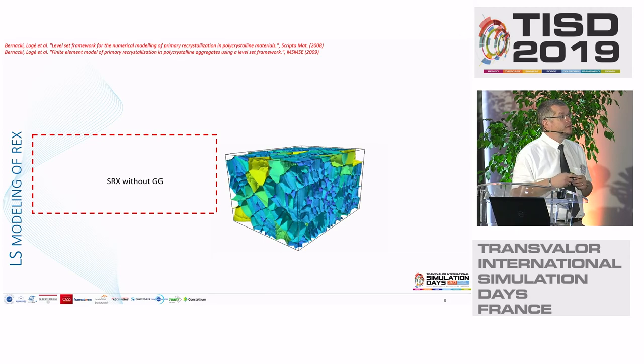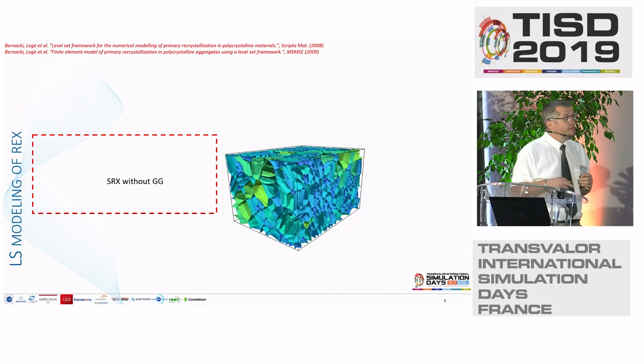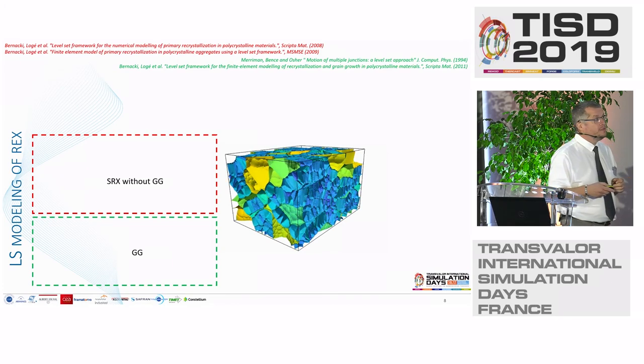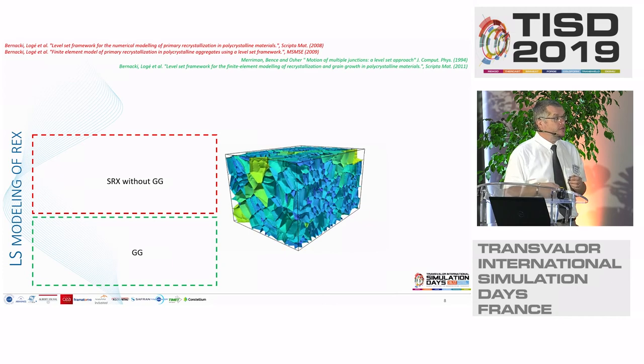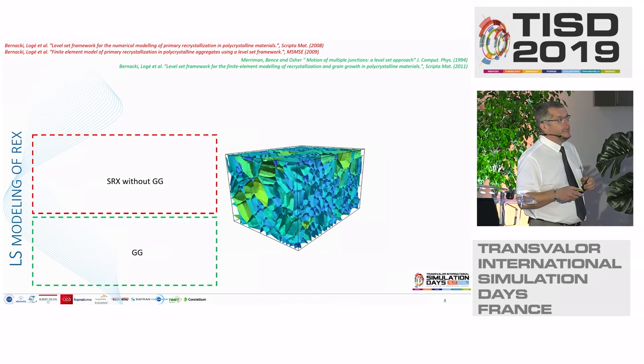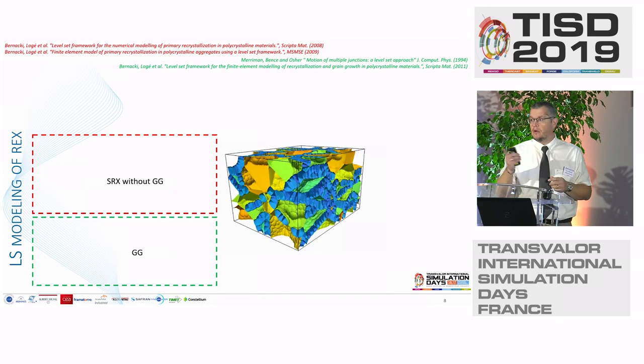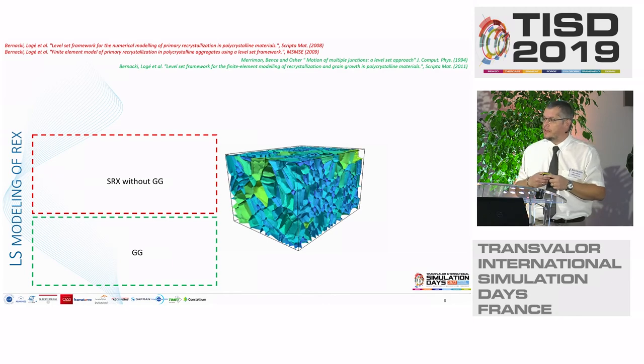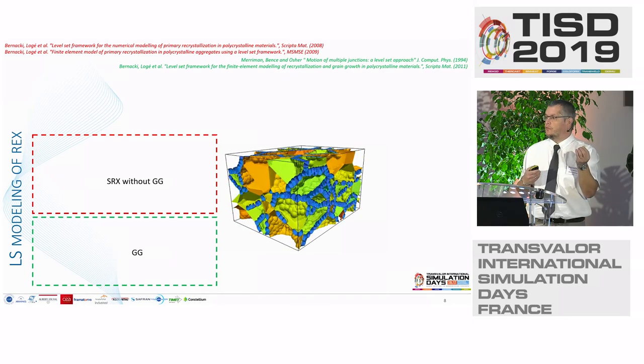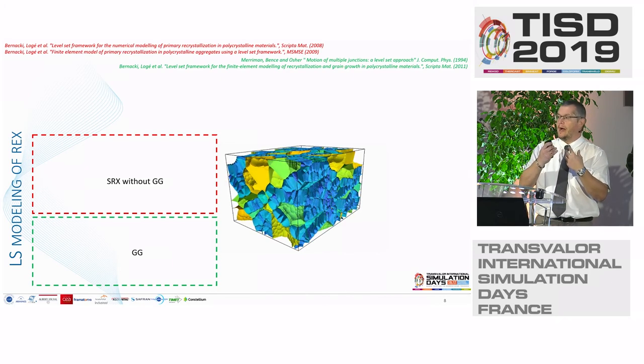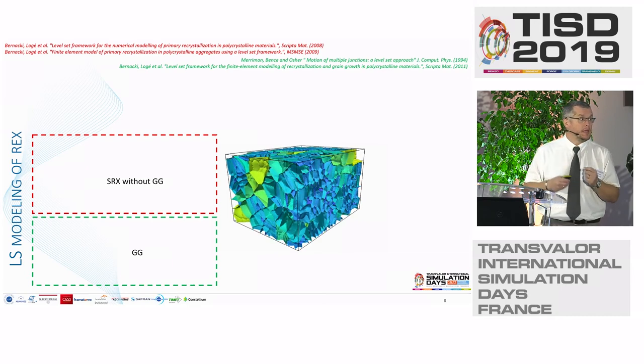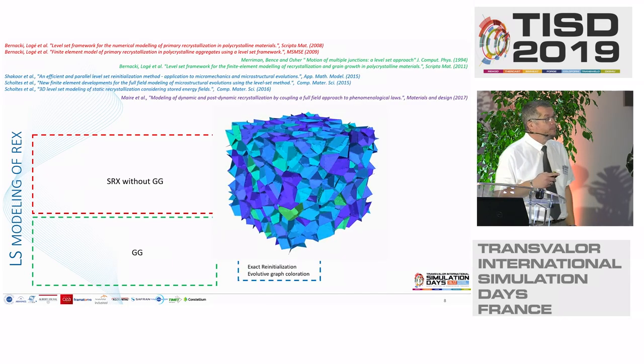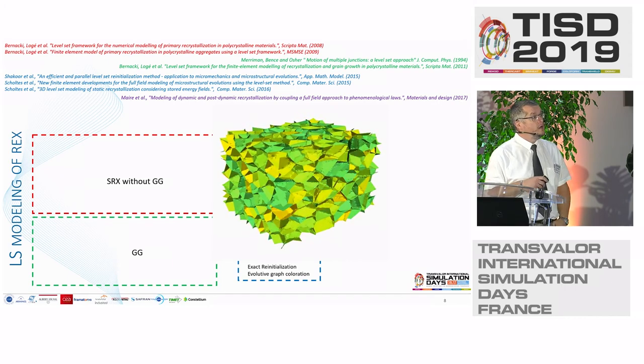Looking at the history of Digimu development, a simulation realized 14 years ago only addressed static recrystallization without grain growth. This framework was then improved to take into account minimization of grain boundary energy through grain growth — discontinuous recrystallization modeling. To simulate continuous recrystallization, you must take into account orientation of nuclei — meaning nuclei appear by local reorganization — and prediction of the orientation of these new grains is something we are now working on for the next version of Digimu.